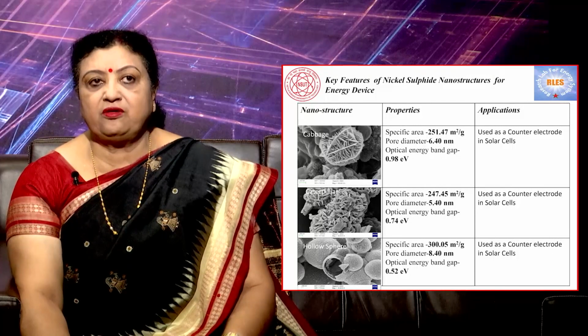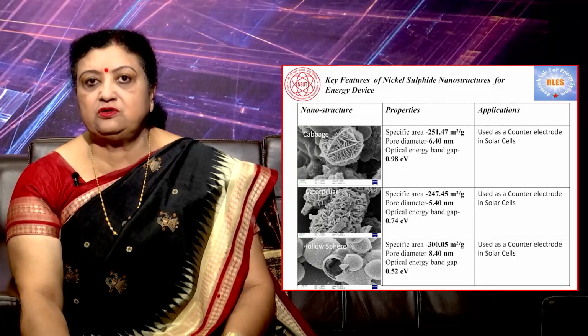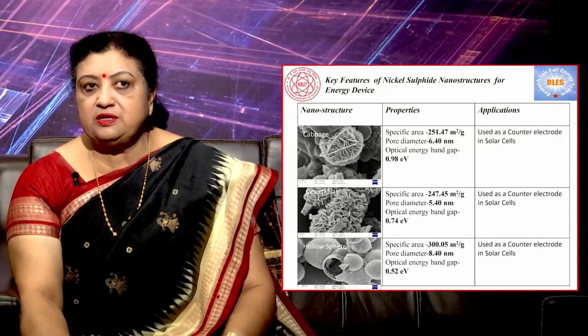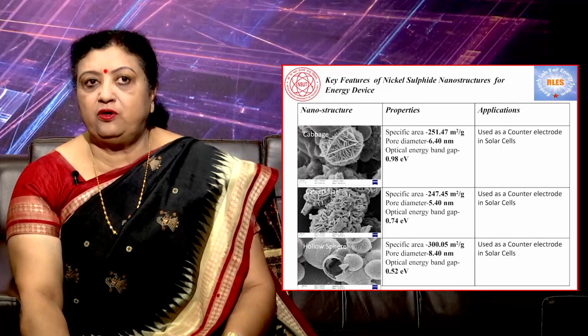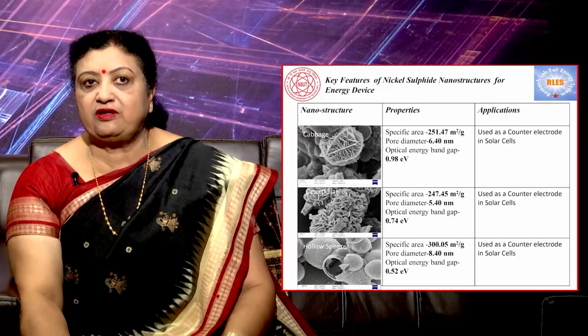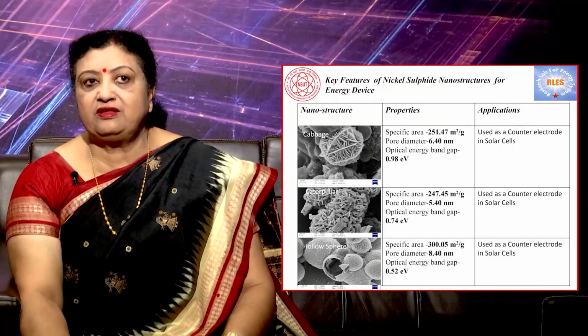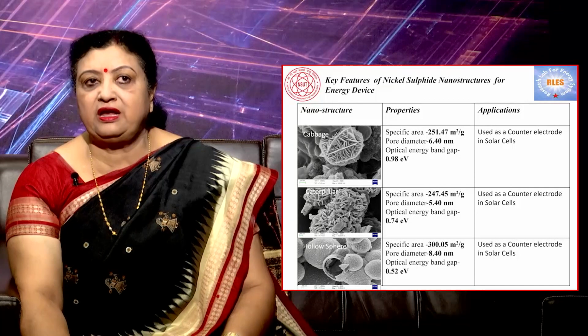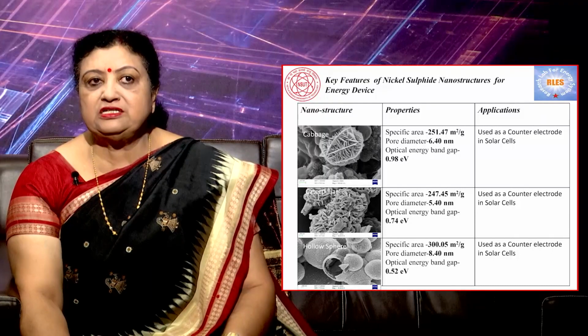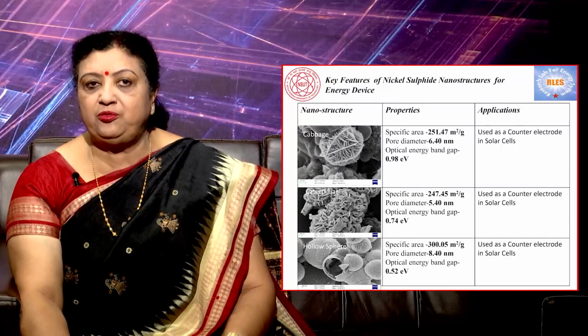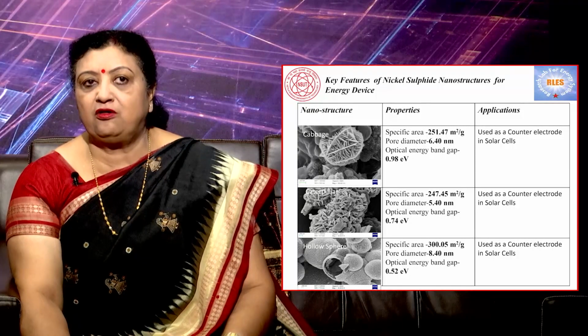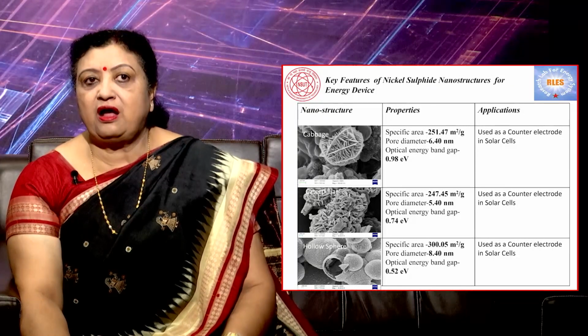Pore diameter is of the order of 5.40 nanometer. Optical energy band gap is 0.74 electron volt, and this can also be used as a counter electrode in the solar cells. The hollow spheres have a specific area of about 300 meter square per gram, pore diameter is 8.40 nanometer, optical energy band gap is of the order of 0.52 electron volt, and this can also be used as a counter electrode in solar cells.